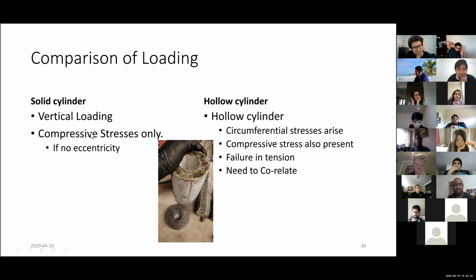So in a solid cylinder, there is just vertical loading, and if there is no eccentricity, there is just compressive stress. There is no other stress there. But in a hollow cylinder, what I found is that circumferential stresses arise due to basically Poisson behavior, due to the Poisson's ratio. And compressive stress is present since we are loading from the top, but when I tried to fail them, they all failed in tension like this. So there is a straight crack going. This shows that there is basically a tensile stress developing inside this cylinder, and this is leading to the failure.